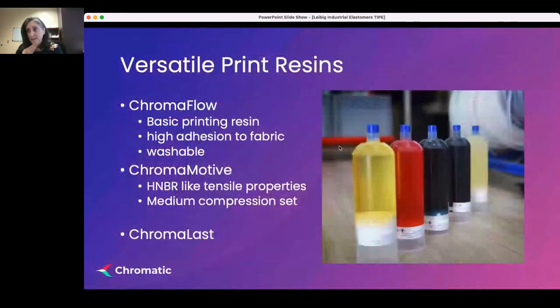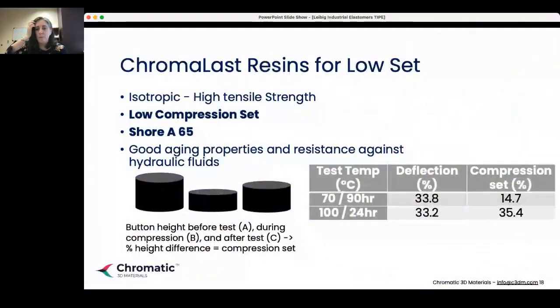So we have a range of resins that we print with. Some that have better compression sets, some that have better tensile properties, usually in a range of hardnesses. We're really excited about our ChromaLast resins that have very low compression set. And this is really important for a lot of seals and gaskets where they need to be sealed under pressure and then be able to maintain their strength and rebound.